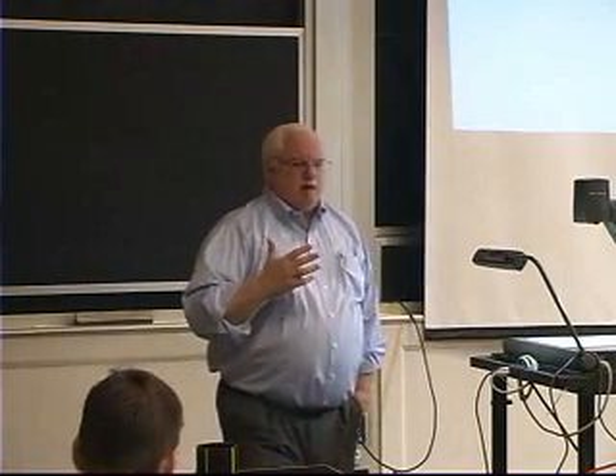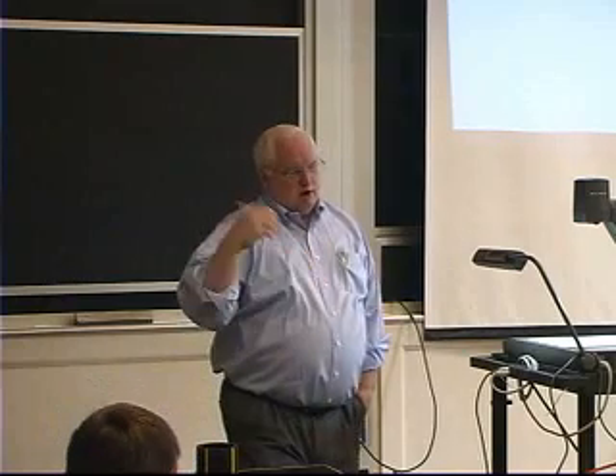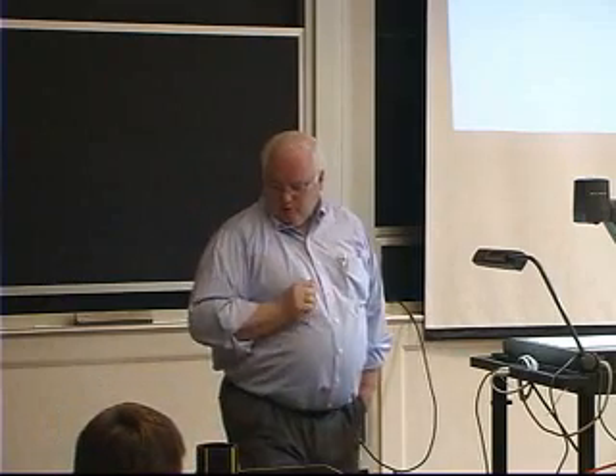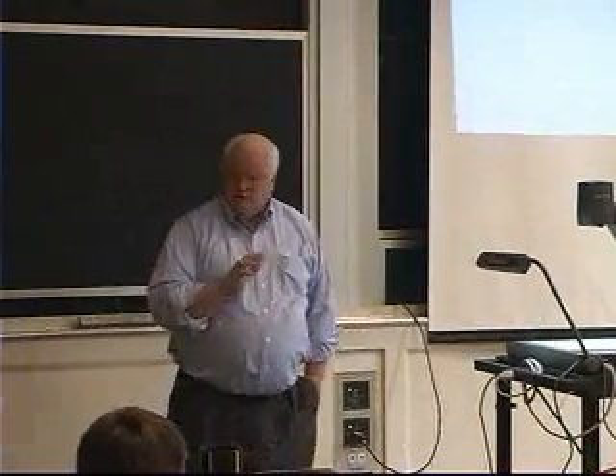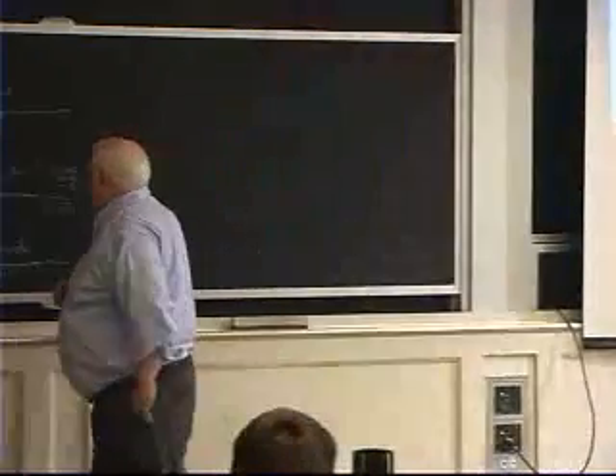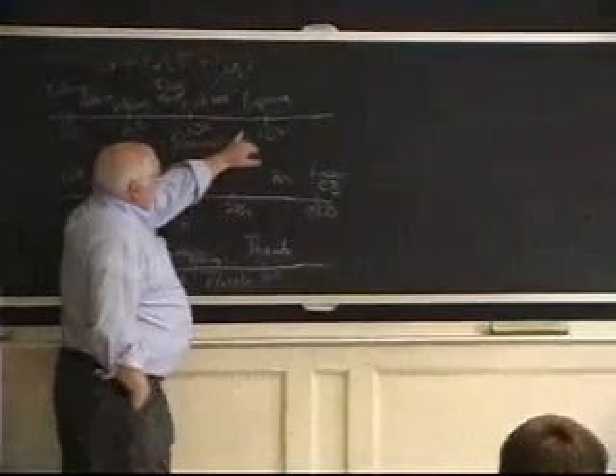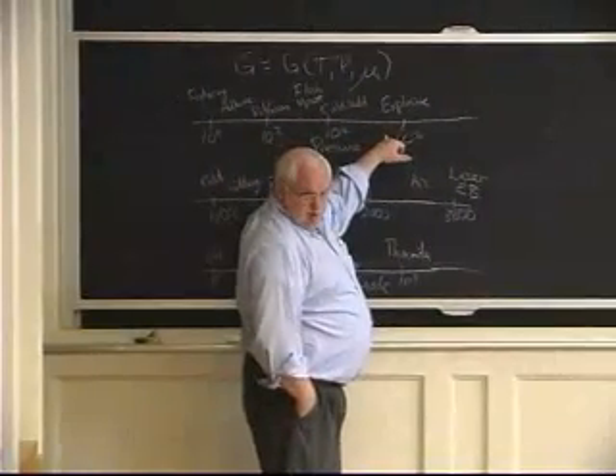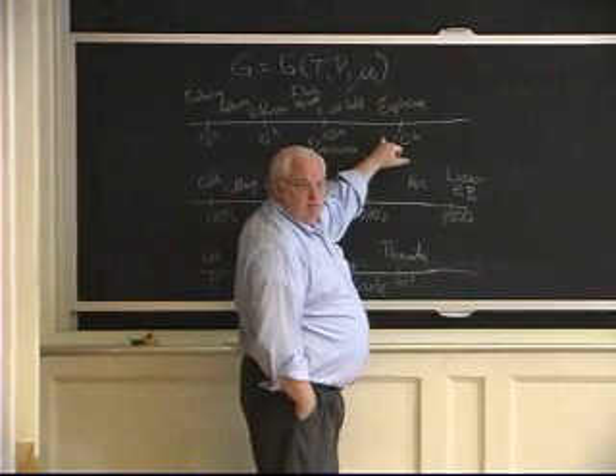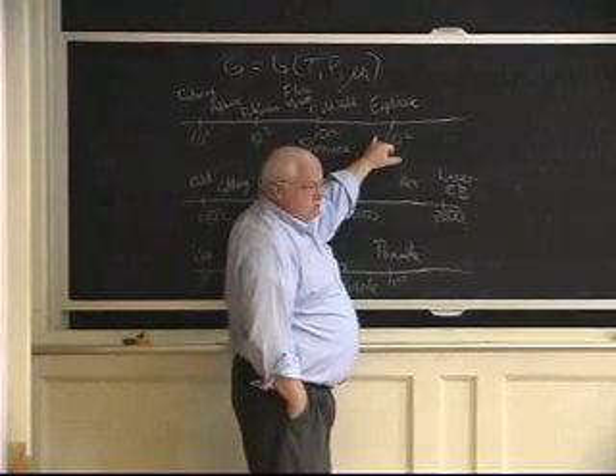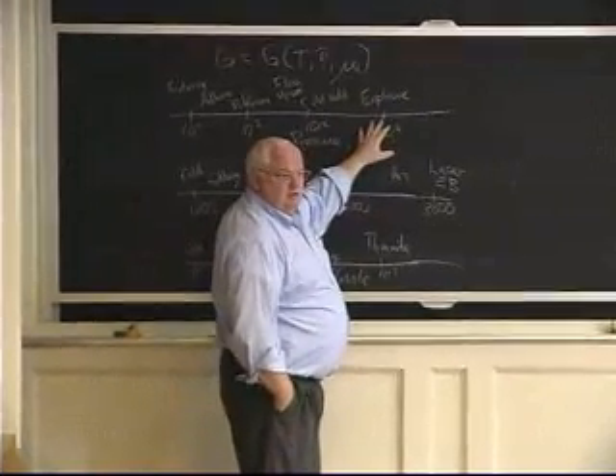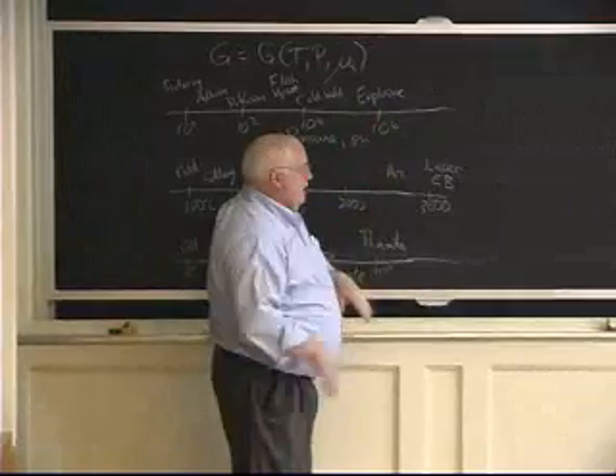And if you do it with the right parameters, you basically tear apart your machine, but you also make a weld. The reason it hasn't been used for welding in the past is because it's pretty hard on the equipment. But you'll generate pressures in the 400,000 to a million psi range. With those type of slamming together pressures, you don't need anything else to clean the surfaces, if they're coming in at the right angle.